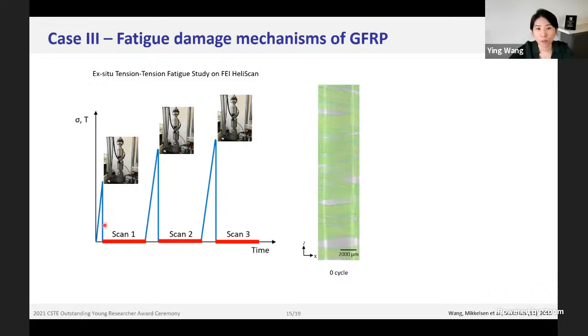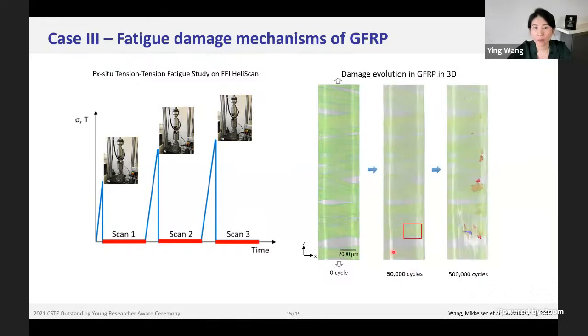As you can see, we employed an ex situ approach to fatigue the composite for a few thousand cycles, then do a scan, interrupt the fatigue testing at different stages and repeat the X-ray CT scan. In this case, we managed to locate that the damage initiates in the vicinity of the crossover of binder yarns in the material, which is really helpful for us to understand the damage initiation mechanisms. And in this study, we use the helical imaging strategy, so we can image the long fiber composite at high resolution in one go. You see the dimensions between the width and length are very large in this case.